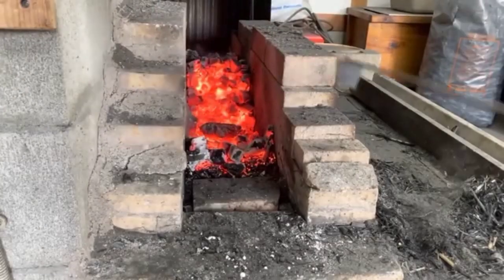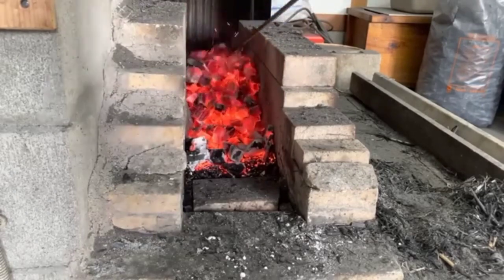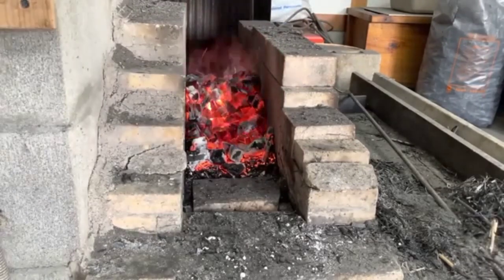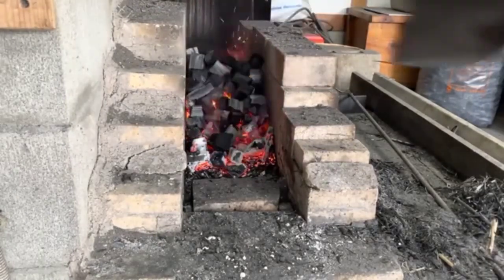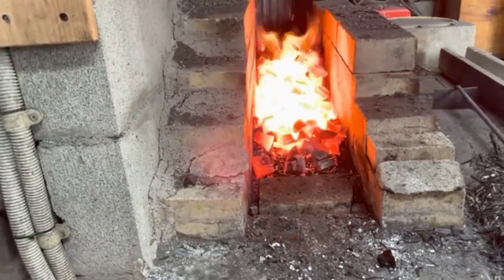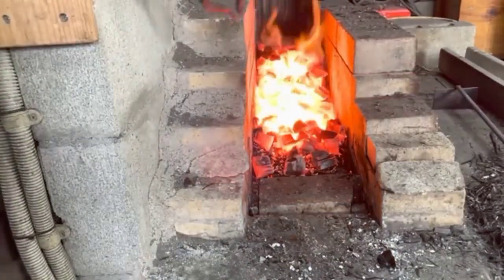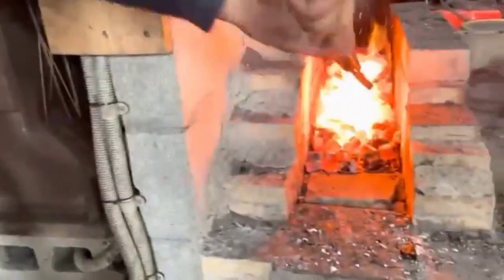Making it unsuitable for heating at excessively high temperatures. When the boric acid melts, it forms a coating on the welding surface of the steel. Then, when the steel is hammered, the molten boric acid expels impurities, removing the oxide layer and allowing the steel to bond properly.